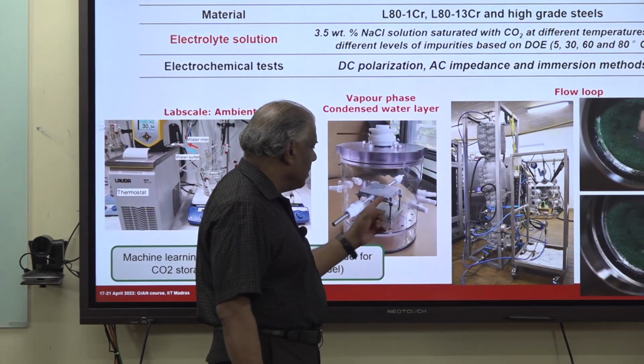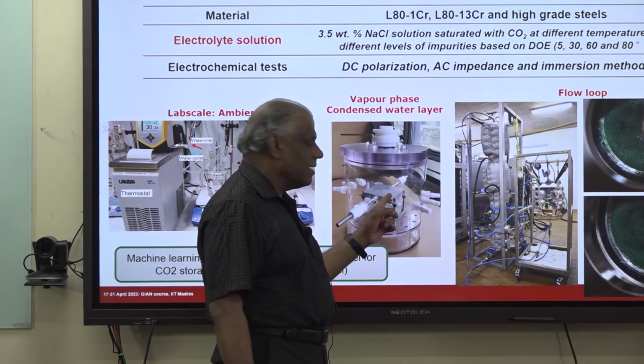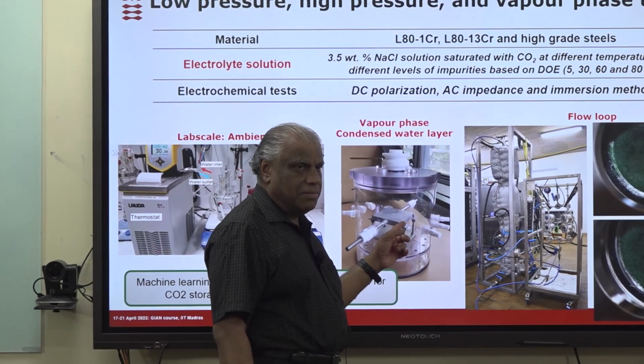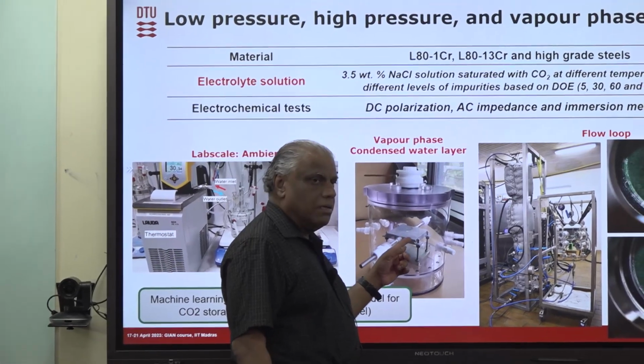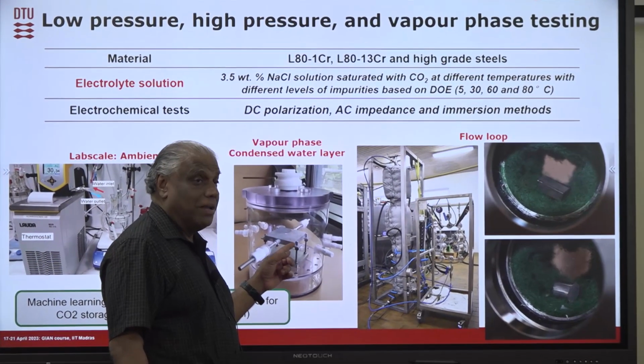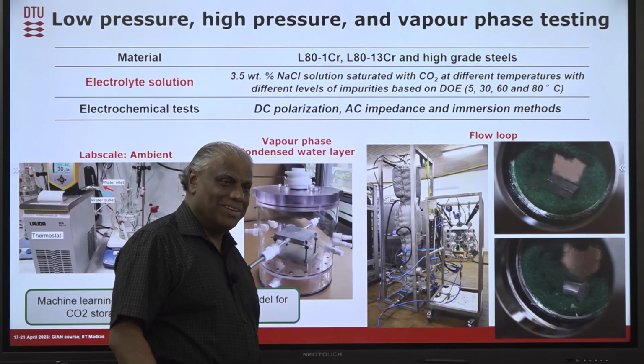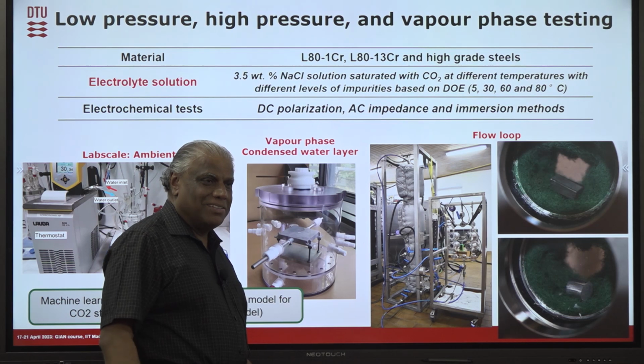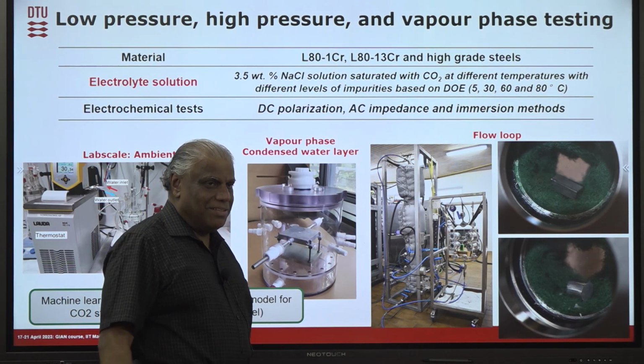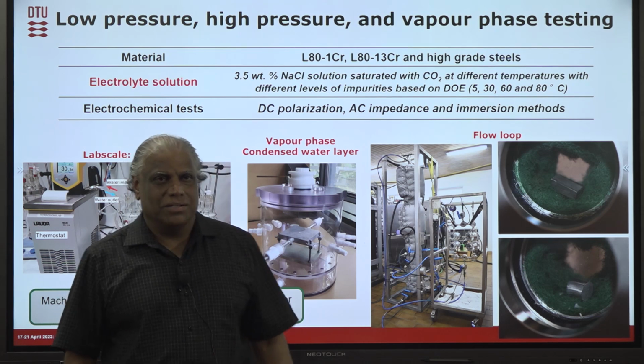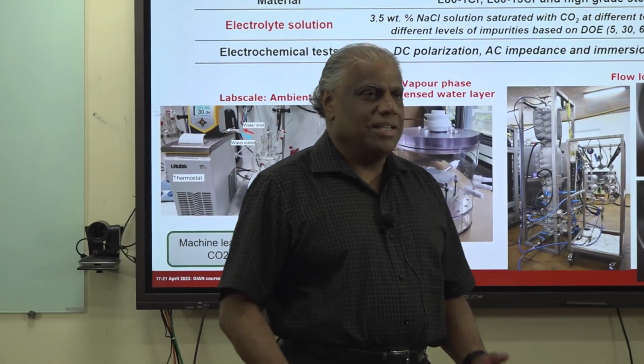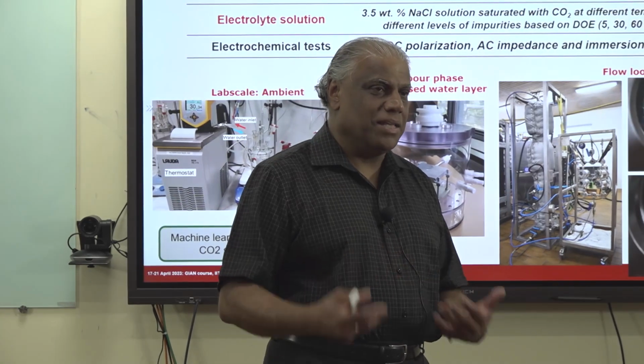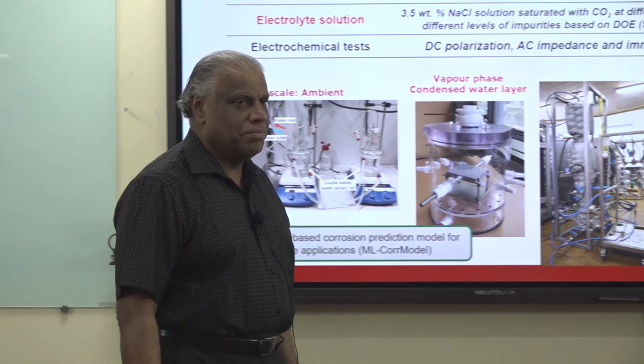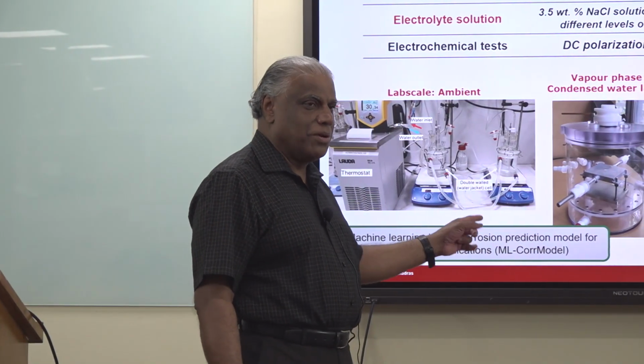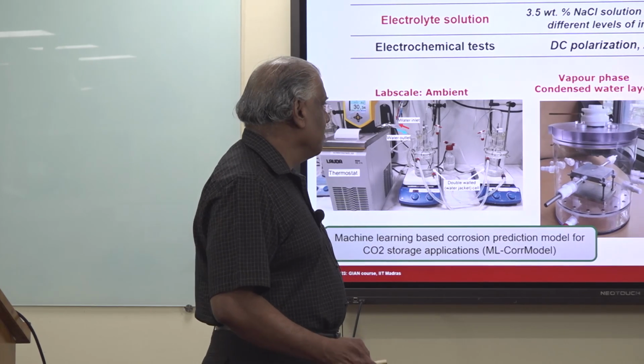Yes, you can control the water layer thickness by adjusting the temperature. We pass a coolant through this, and depending on the coolant temperature, we can control the water film thickness. We can go down even to 1 micrometer or lower. We can go really lower. The question is what thickness level we can measure. Probably 100 nanometer to 200 nanometer is the level at which you start seeing that the electrochemical current can pass easily, and that way you start getting the problem. Let us discuss that tomorrow, because tomorrow I'm going to show more things related to that.